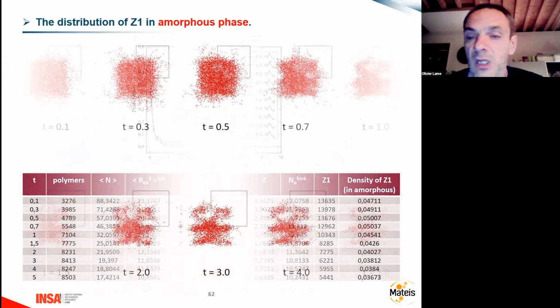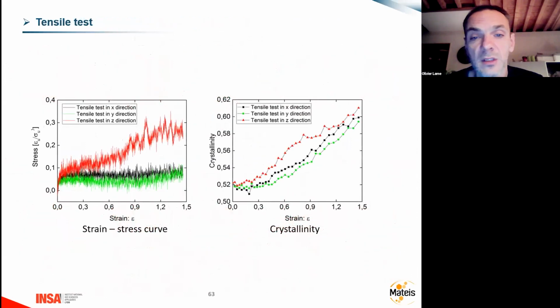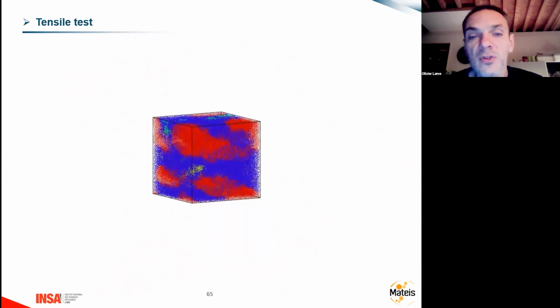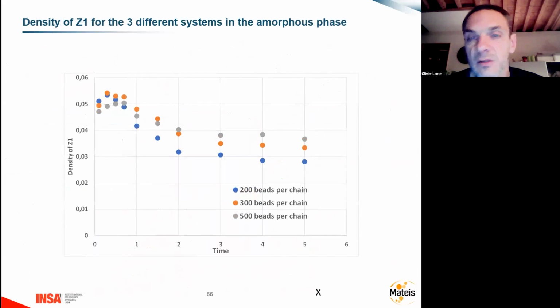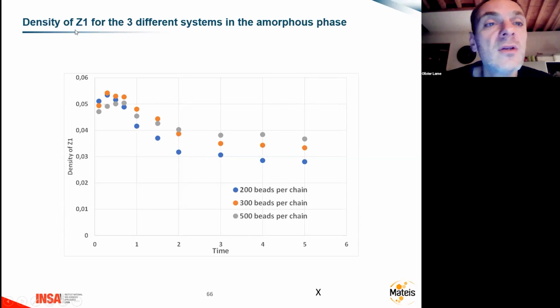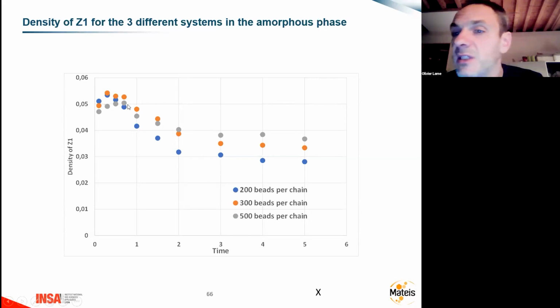But now what is very interesting is to compare these three systems together. I will not compare everything, because it's a huge amount of data. I will compare only two things. The first is the density of entanglement in the amorphous phase for the three systems, 200 beads, 300 beads, and 500 beads, versus the time of crystallization. You see that this density is decreasing, which is quite an important result and not so easy to understand, because we could have thought that the density of entanglement should increase with crystallization if we push the entanglement into the amorphous phase and if we don't destroy it.